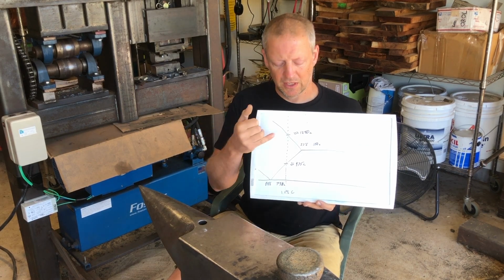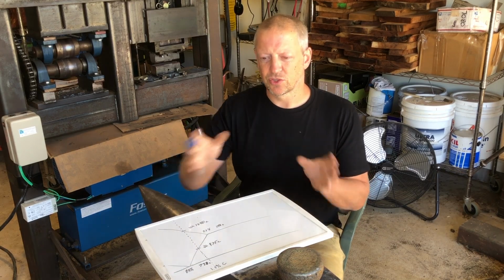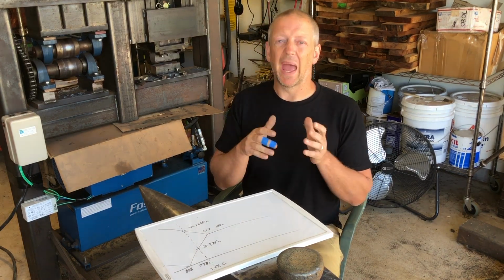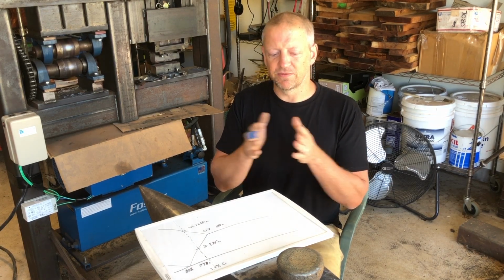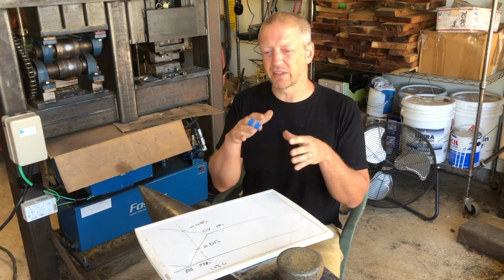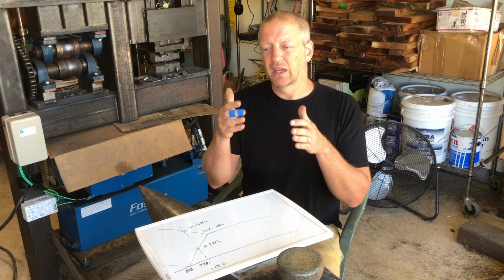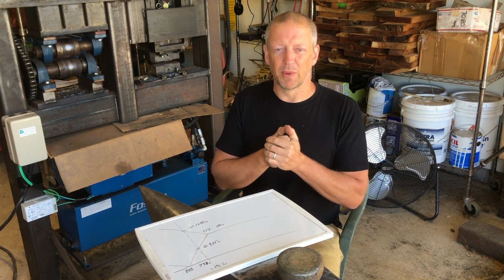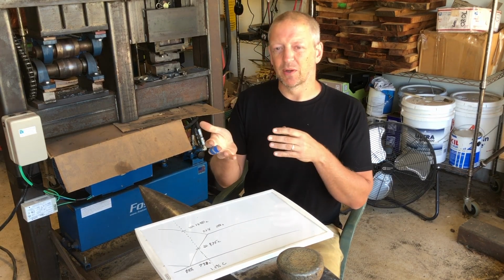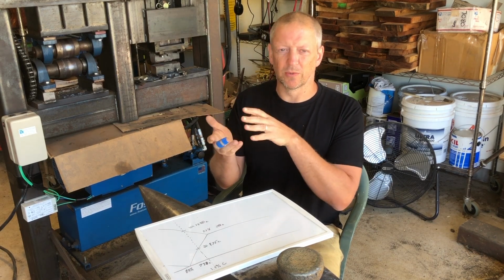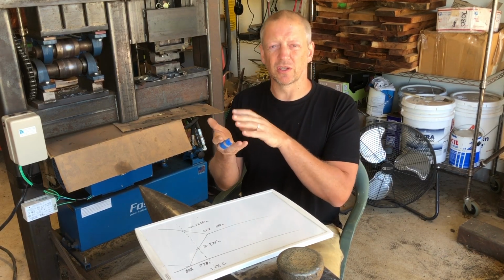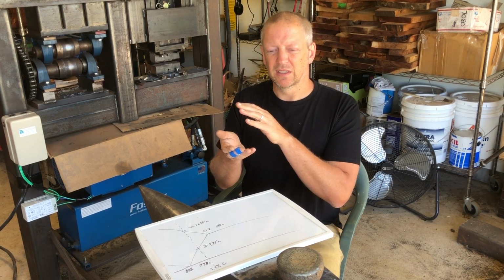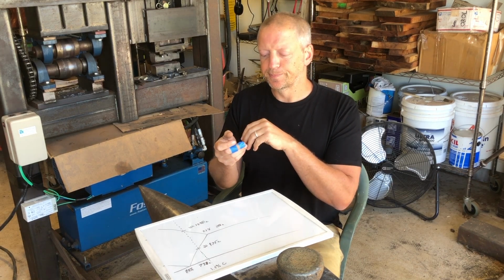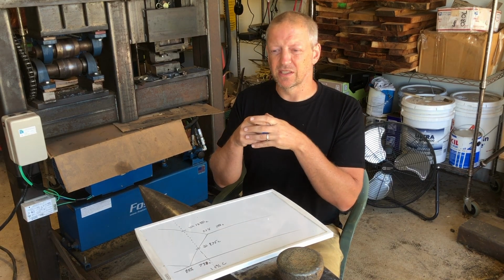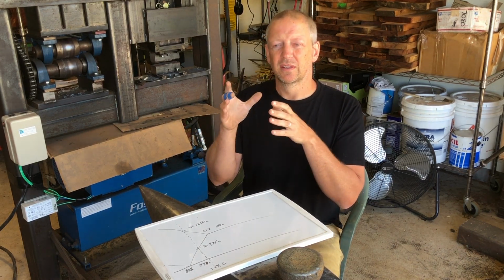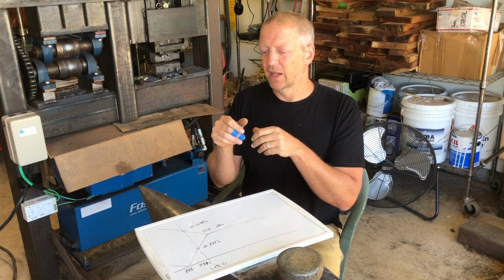This brings us to the result. That grain boundary carbide structure isn't necessarily bad, because what it tells us is that our carbon diffused pretty much completely. So we had a relatively even carbon content throughout, and then we precipitated grain boundary carbide, which isn't something we want in our final knife or sword or whatever it is. Grain boundary carbide is a terrible structure when it comes to actual physical characteristics. However, the fact that the carbon is relatively evenly dispersed, definitely a lot easier to forge at that point.